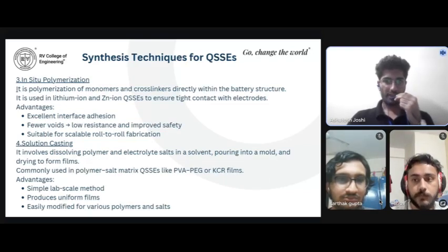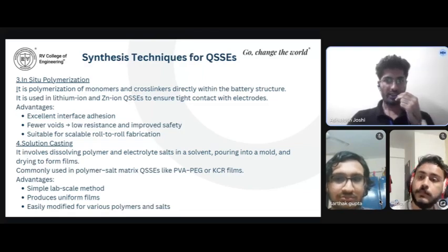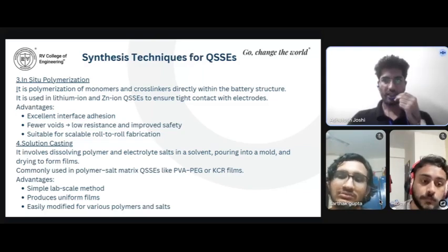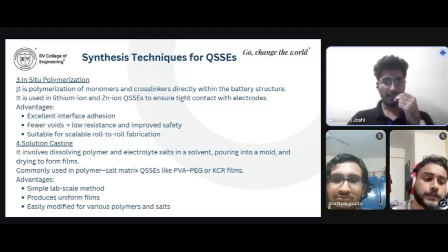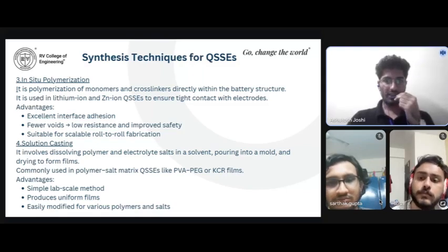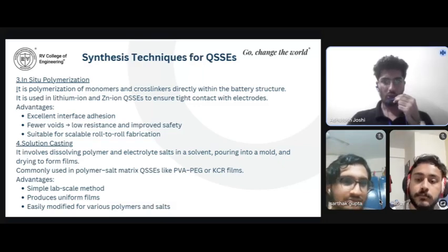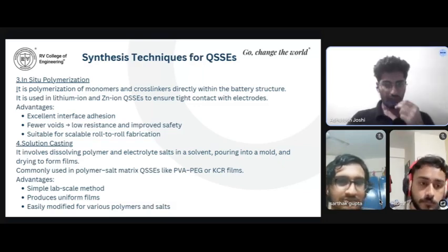Third, we have in situ polymerization. Its mechanism includes monomers and cross-linkers being introduced in liquid form directly into the battery's housing. Polymerization is then initiated within the battery either thermally, chemically, or by UV light. Its application is in lithium-ion and zinc-ion QSSEs, where it ensures uniform coverage and minimal interfacial resistance. Its benefits include excellent interface adhesion as the polymer forms in direct contact with the electrode surface, filling all voids and cracks, reducing electrical resistance and safety hazards, and being compatible with scalable manufacturing methods, including roll-to-roll fabrication, making it industrially viable.